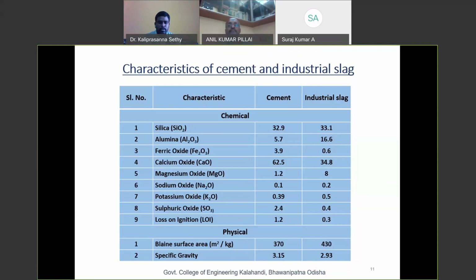And you can see the chemical composition of cement and this slag. It contains almost similar silica content as cement, and the Blaine surface area is 370 square meter per kg for cement, whereas the industrial slag which we used here has a surface area of 430 square meter per kg. So it is finer than the cement which we have used for the design of self-compacting concrete.